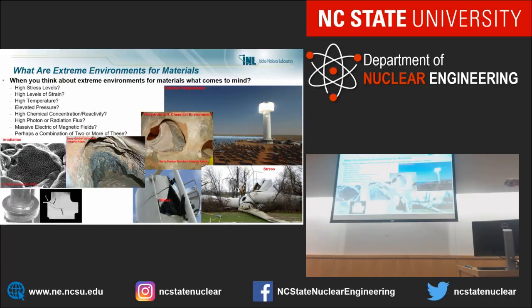That is a solar collecting panel for concentrating solar power. All these mirrors are on a gimbal, shines up here. This can go up to about 550 degrees Celsius. Now we are in Gen 3, and Gen 3 is upwards of 700 degrees Celsius. How do you create materials that can do this and do this consistently every day? And when the sun rises and then sets at night, your temperature variation could be over 200 degrees Celsius. And you do that every day for years on end. How do we do this?